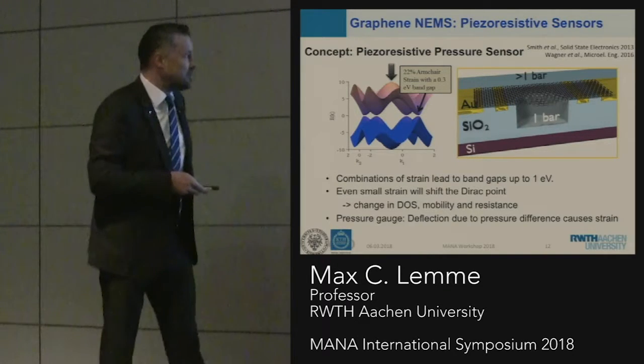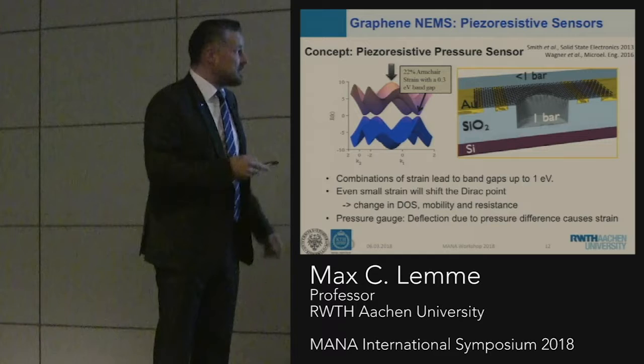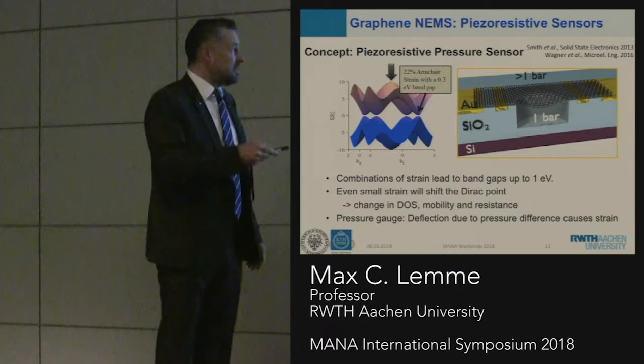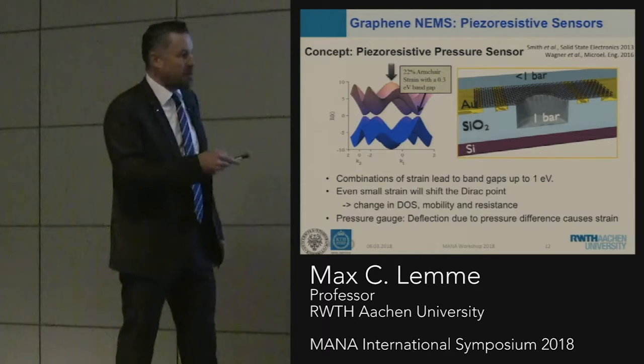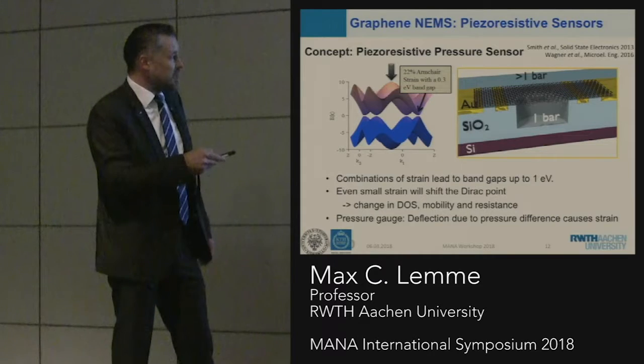This is what we try to use in a device where we had a cavity with a pressure of 1 bar trapped inside. By changing the pressure on the outside of this cavity, the graphene membrane gets deflected, and because it's piezoresistive, we can measure this directly.